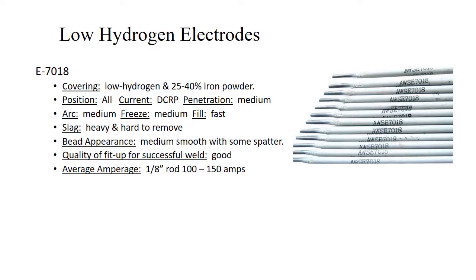With our low hydrogen electrodes like E7018, we're going to have a little more iron powder than we would have in 6010. This is going to give us a little higher deposition rate. All position, it's got a medium arc. The freeze is going to be medium. The fill is going to be a little faster. It's got a little heavier slag than 6010 does, and it's a little more difficult to remove.